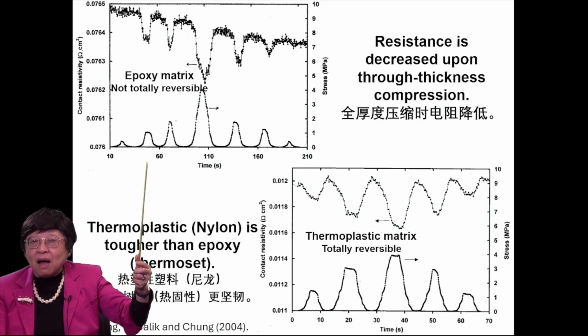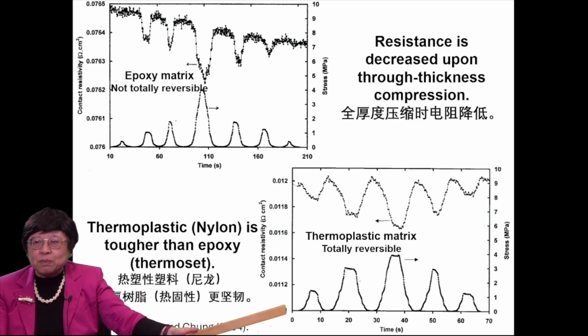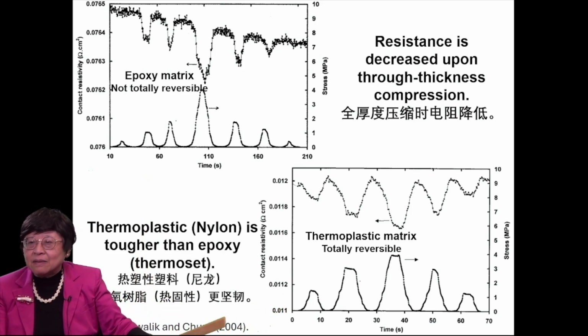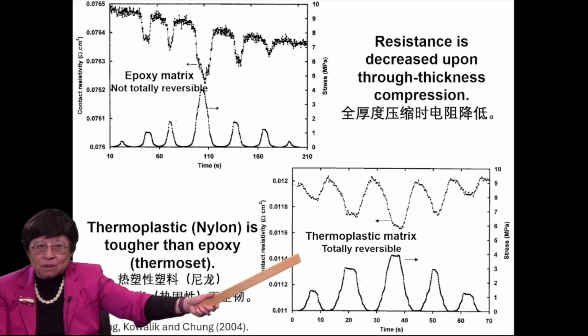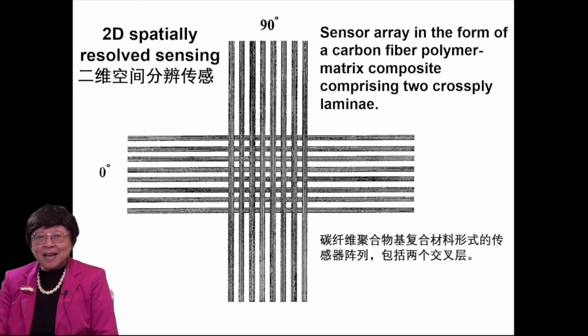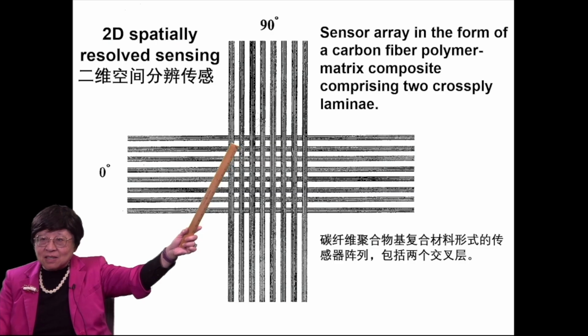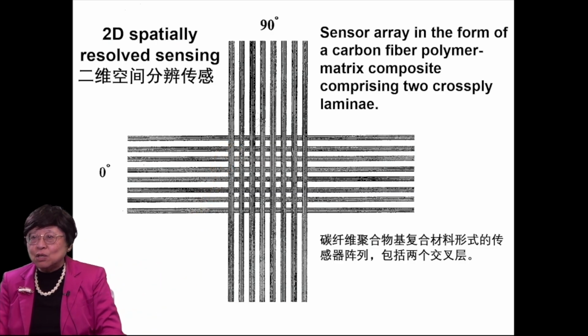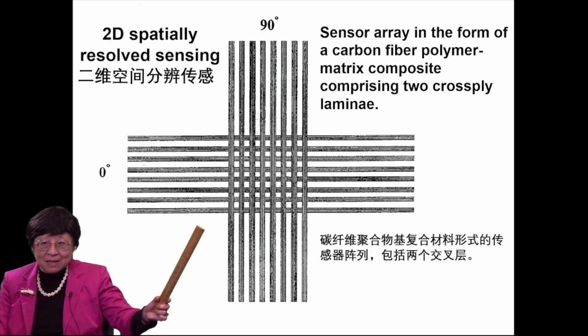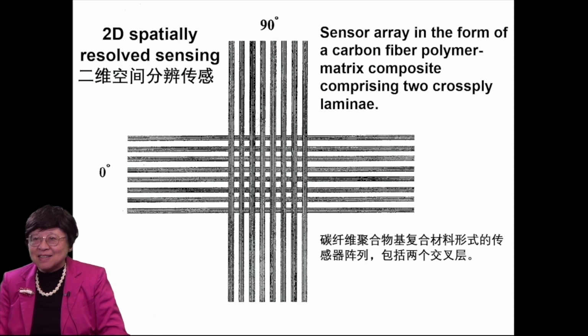However, if instead of using an epoxy matrix, one uses a thermoplastic matrix, then we have total reversibility. Another nice thing about contact resistance measurement of the interlaminar interface is that one can have 2D spatially resolved sensing, because each overlap region is one sensor. So you have a 2D sensor array. And in this case, you have two cross-ply laminae. They don't have to be 90 degrees, but this is drawn 90 degrees. And anyway, you have 2D spatially resolved sensing achieved.